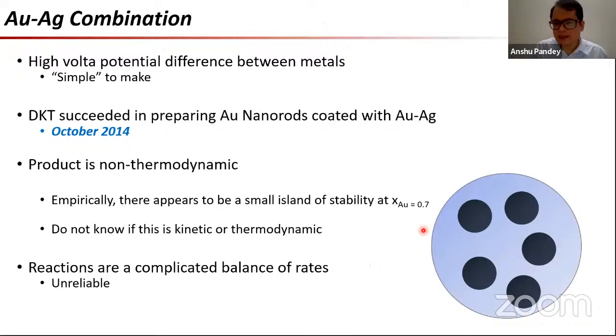Now, why is any of this relevant to AuAg? Well, the reason why we would pick AuAg is precisely this earlier data. While these metals are very, very similar, gold and silver are extremely similar metals. They even have the same lattice constants. They have a high Volta potential difference, or a high contact potential, or a high electrochemical work function, either way we play with the words, which exists between these metals, which means that Au and Ag actually have a natural tendency to transfer charge from one to the other.